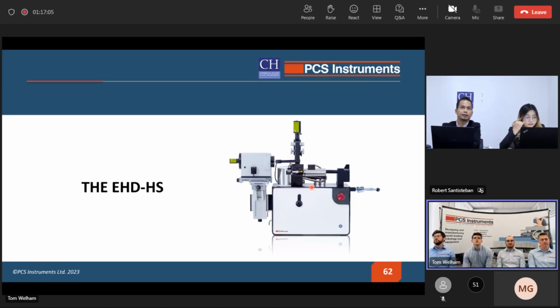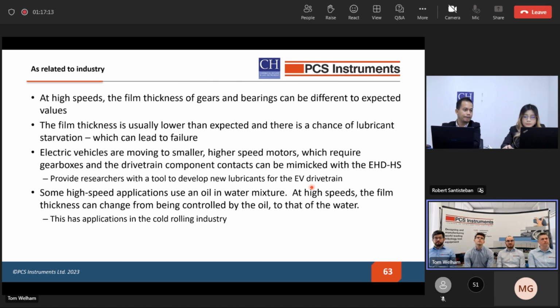So recently we launched a higher speed version of the EHD rig. So I'll talk briefly about the benefits that this brings. At high speeds, various effects such as starvation and shear heating occur, and that can cause film thickness to deviate from expected behavior. Typically, that means film thicknesses are lower than expected, and that can definitely be detrimental to efficiency and life of the component.